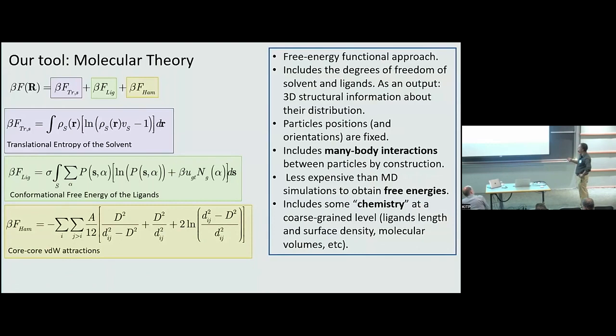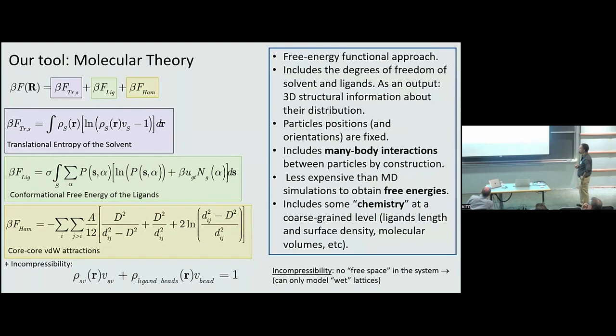I have to say all of this is a coarse grain model, so we don't have atomistic detail, but we still have some control over the chemistry in the sense that we have an explicit description for the ligand, so we can decide the length of the ligand or the grafting density. So there is some chemistry there, but still, this is a coarse grain model. And we have one extra contribution that is an incompressibility constraint, which means that in each point of the space, we have either solvent or ligands, or because this is a mean field, some combination of both, but we cannot have free volume, okay? So we can model wet lattices very well, but not dry superlattices. At the end of the talk, I'm going to show you some results that go beyond this approximation.